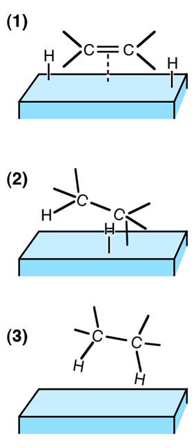Heterogeneous catalysis. On solids, the accepted mechanism is the Horiuti-Polanyi mechanism. Binding of the unsaturated bond, and hydrogen dissociation into atomic hydrogen onto the catalyst. Addition of one atom of hydrogen, this step is reversible. Addition of the second atom, effectively irreversible under hydrogenating conditions. In the second step, the metallointermediate formed is a saturated compound that can rotate and then break down, again detaching the alkane from the catalyst.